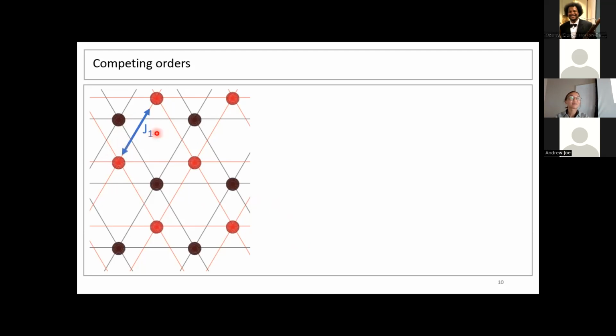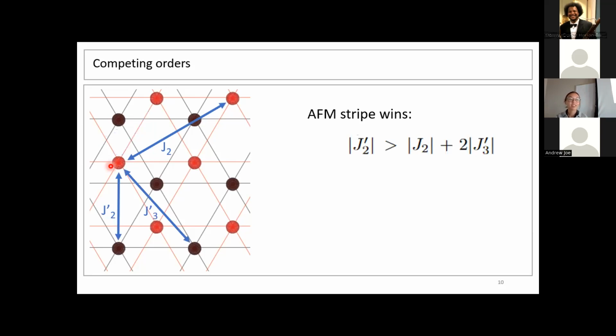So I've shown you that the spins are going to want to point in the opposite direction to their neighbors. But there are many degrees of that. There's your first nearest neighbor, then there's your second nearest neighbor, which will have a different strength of that preference. There's your first nearest neighbor in the next plane. There's your second nearest neighbor in the next plane. There's your third nearest neighbor, etc. And so it turns out it comes down to these three really distant relationships and how exactly they compare to each other. That's what's changing very slightly when we change the amount of iron and leading to this really dramatic qualitative difference in what the magnetism is doing. So in one case the stripe wins and in the other case the zigzag wins.